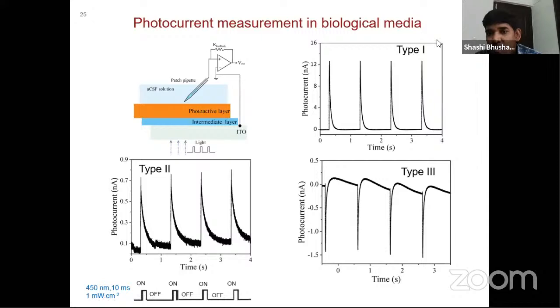So with type 1, we saw a very high Faradaic current, like 12 nanoampere, which is not good for our devices. Then we went to the molybdenum oxide device, which is type 2, and we saw that this Faradaic current is controlled a bit. In fact, hugely controlled. It's 0.7 nanoampere only. But when we put the zinc oxide, it shows the capacitive behavior of the charge transfer. This is the charging, and it is reversed, because when we put zinc oxide, the holes start moving towards the protective layer, and towards the ITO it is the electrons. Because of that reason, it is reversed. So this is the charging, this is the discharging. There is a slow discharging, which is related to the material property.